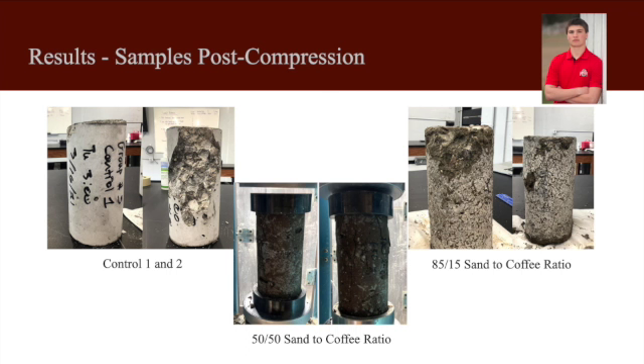The biggest thing that was observed was how the control sample failed compared to how the samples with the coffee grounds failed. The control sample looked as if it broke off in chunks, as you can see on the left side, and the time span of the failing was almost an instant. For the coffee grounds, the failure was more of a crumbling, and the crumbling took place over the duration of the test.